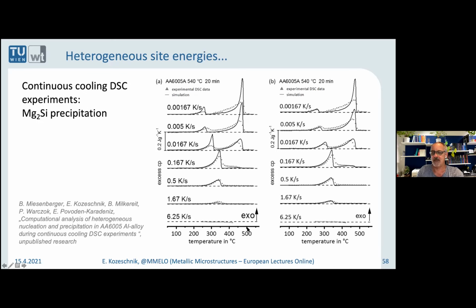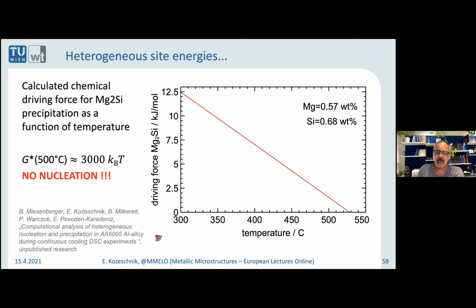Because when you look at the system here, when the alloy is cooled, the DSC signal comes up roughly at 500 Celsius. So I said, okay, I dealt a lot with nucleation theory, so it should be possible to reproduce the experiments. And with everything that I told you so far, it was not possible to get any of these data reproduced. So focus on the roughly 500 degrees where apparently magnesium 2 silicon beta phase will precipitate. When you look at the driving force as a function of temperature, this is the chemical driving force in kilojoules per mole. Roughly at 500, you can see that the driving force is extremely low.